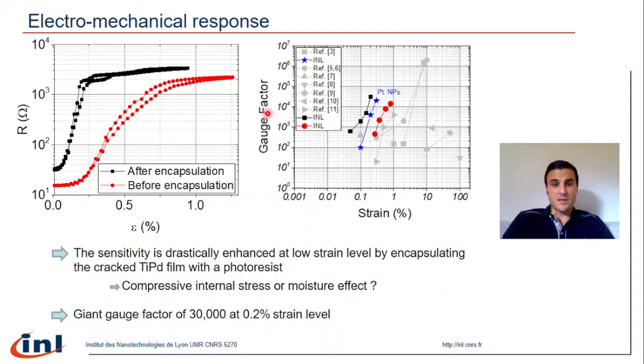From the black curve obtained for the encapsulated sensor, we could extract a giant gauge factor of 30,000 at 0.2%. Here on the right, from this benchmarking, you can see that before encapsulation, our sensitivity is lower than the one obtained with the nanostructured transducer based on platinum nanoparticles. The encapsulation enables us to further increase the sensitivity.